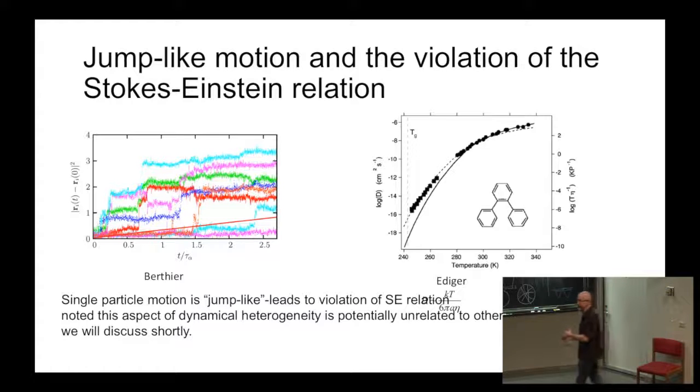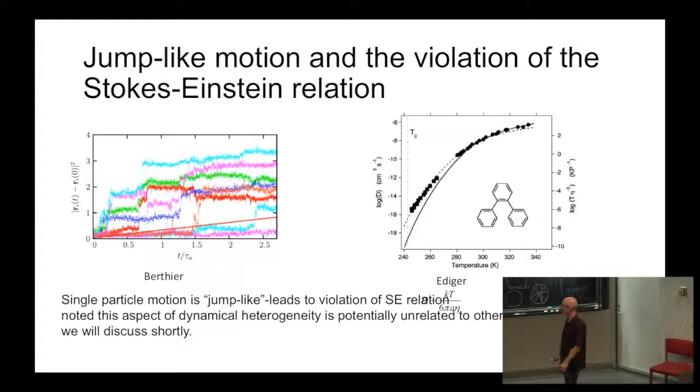The viscosity is dominated by the 95% of the particles that aren't really moving very much. Okay? And so these two things aren't necessarily coupled one-to-one in a simple relationship, and so you see a large difference, on a log scale, between what the actual effective Stokes-Einstein relationship is and what you would expect from Einstein's calculation.